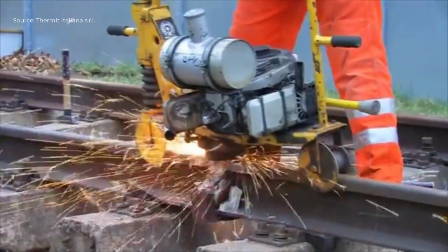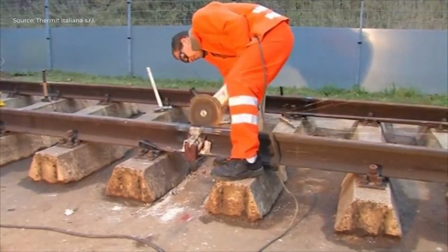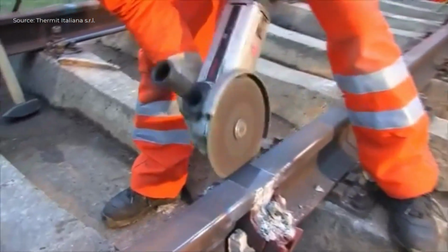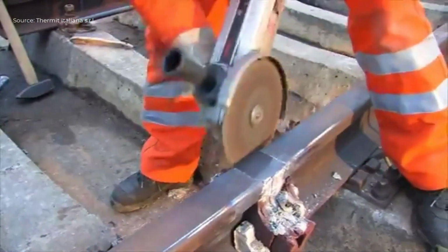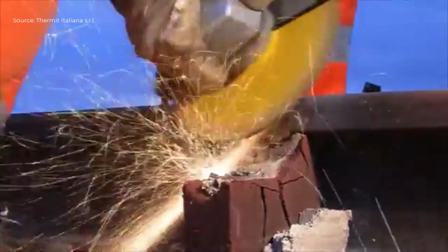After pouring, the crucible and slag pans are removed and placed on a non-flammable surface. The molds remain in place for a specified cooling period. Once solidified, the mold head can be removed, and the excess material is removed using a hydraulic trimmer. Therefore, a small oversize can remain after rough grinding. Final grinding is done to restore the rail profile to its original specification, including the running surface, radius, and flanks. The rail could now be passed by a running wheel.